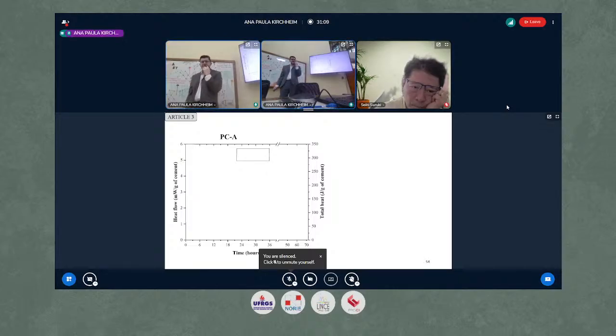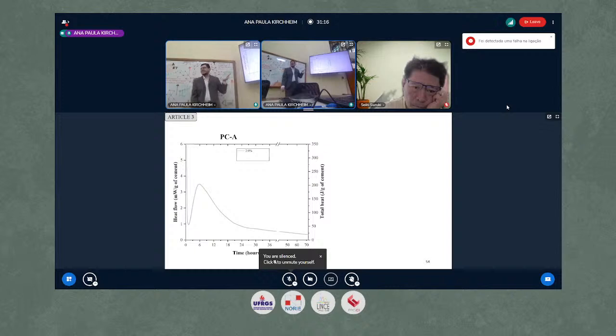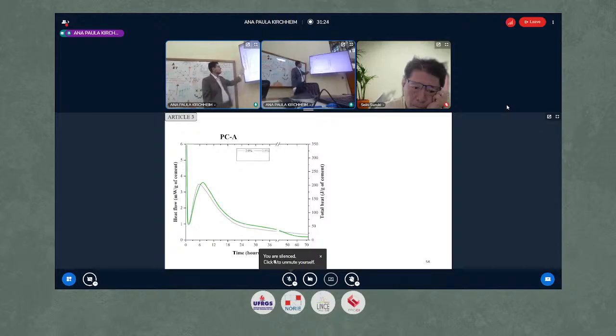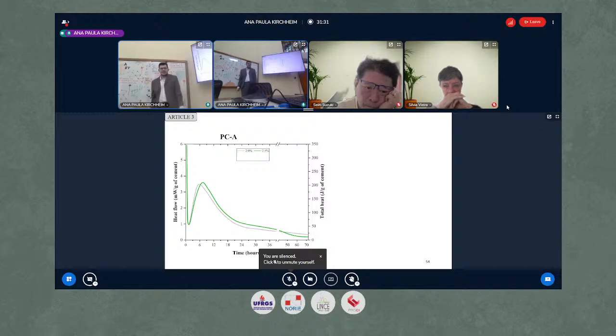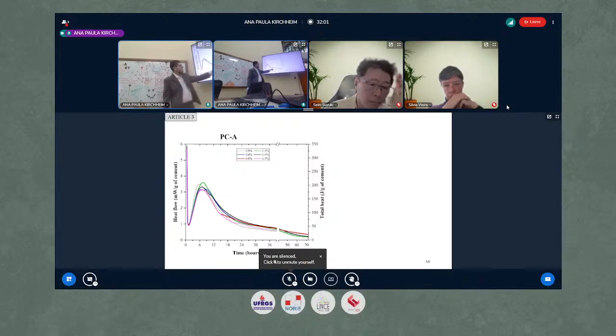So in the first clinker, here we see first with the lowest level of sulfate, 2%, clearly an undersulfated mix, because we don't see the shoulder peak. When we add more sulfate, 2.5%, we see a variation in the main silicate peak, but we also don't see the shoulder peak. When we reach 3%, we now see the shoulder peak. So we are reaching the optimum. Then we go to 3.5%, and we see this shoulder peak in a few hours. So I would say that the optimal content would be something between 3 and 3.5. Because when we go to 4%, we see the shoulder peak here. It's very late. And at 4.5% it is here.